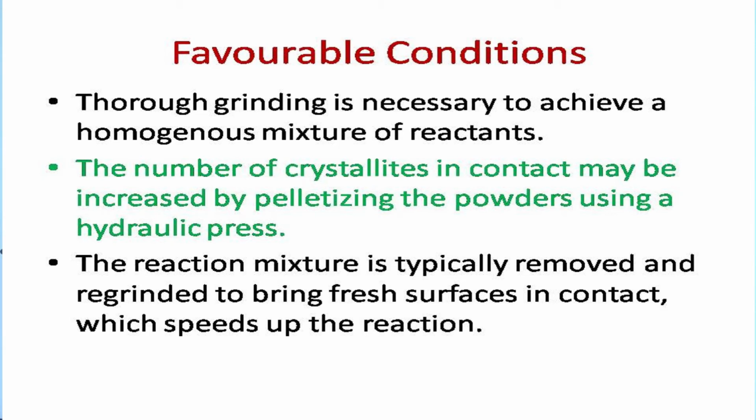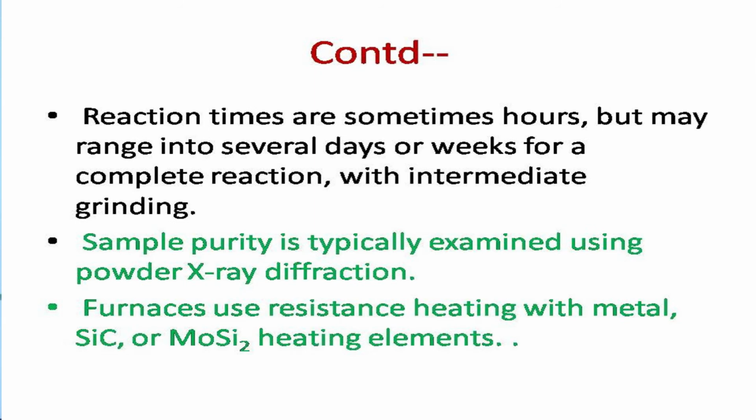Now this third step that you have seen in this slide is this: sometimes when the reaction is in process, you stop the reaction after a certain interval, cool the mixture, bring it out, and then grind it so as to expose fresh surfaces to be in contact, and this process will speed up the reaction. Although the temperature plays its role in speeding up the reaction, by bringing new surface contact areas, the reaction will also speed up. So this is a very important aspect: while the reaction is on, you stop it, cool it, regrind it, and restart your reaction in order to complete it to the required level.